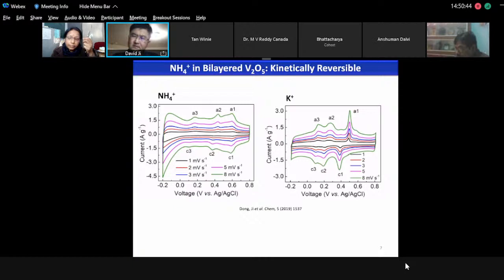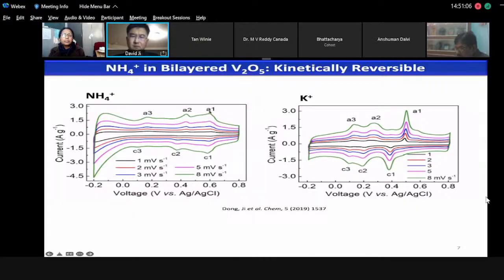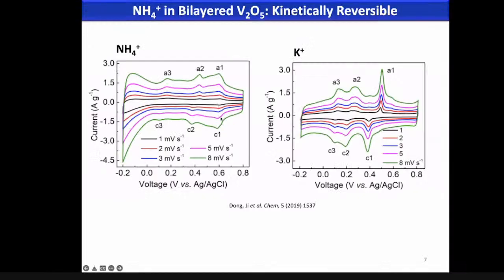And it turns out that is pretty significant. If you look at the performance of the same V2O5 bilayered structure to store potassium ion, it's typical. You call it battery performance with the peak separation, and then for ammonium ion, you have this vertically aligned, and we call that kinetically reversible behavior. And this is something we call diffusion-free, non-diffusion controlled. I apologize, non-diffusion controlled. Okay, so all we call it, capacitive.